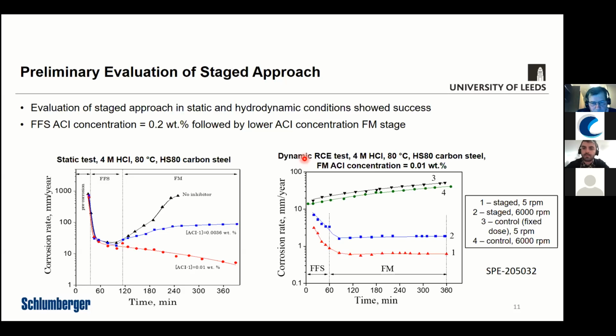Introducing flow into that, in laminar flow and turbulent flow conditions, depending on the rotational speed of the RCE, the staged approach, which is the blue and red lines, was still effective in the different flow conditions. But when comparing to lines 3 and 4, which were control tests, so they were done at a fixed concentration of 0.01 weight%. And in this case, it's comparing with the film forming stage at 0.2 weight%, followed by 0.01 weight% film maintenance stage concentration.